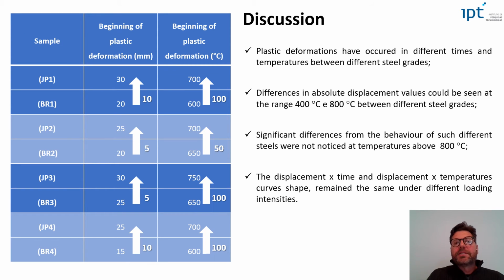Some points were discussed before the conclusions, based on the results showing the beginning of the plastic deformation in millimeters and in Celsius degrees. As we can see, the other tests show different numbers, but always demonstrating the same ability to reach the plastic deformation when using fire-resistant steel.